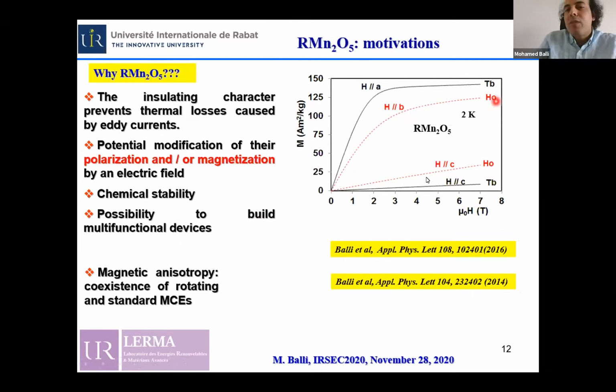From this figure, we can see, for example, that along the easy axis, the holmium and terbium compounds unveil large magnetization values, while along the hard axis, the magnetization is very low.